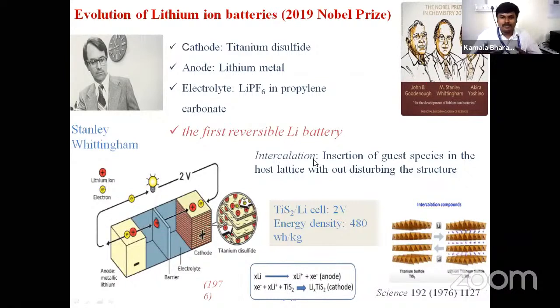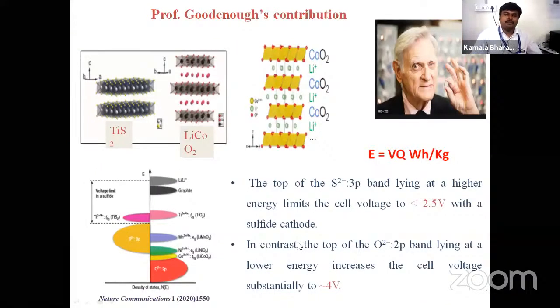Intercalation is nothing but what I showed in the cartoon just now, where the lithium goes back and forth between the cathode and anode. So he was able to demonstrate a battery with 2 volts and an energy density of 480 watt hour per kilogram. And then Professor Goodenough's contribution was that he replaced the sulfide based cathode with a transition metal oxide based cathode. The advantage of using a transition metal oxide based cathode is that we can have a higher voltage.